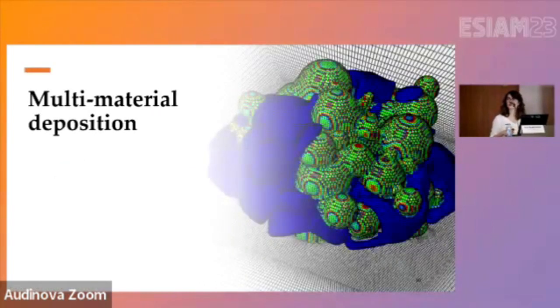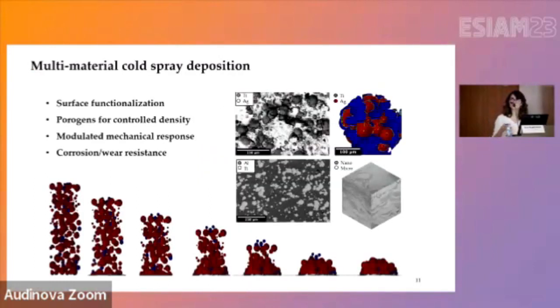The next topic I would like to briefly touch on is how to correlate the process parameters to the mechanical performance of the structure. It's very useful to be able to mix different materials for different purposes. What we have done in our group is that we have sprayed mixtures of blended powders for surface functionalization, for using one powder as a porogen in order to remove it and get a porous structure, or modulating the mechanical response because of the synergy between two materials that have very different mechanical properties, or for, let's say, corrosion or wear resistance.